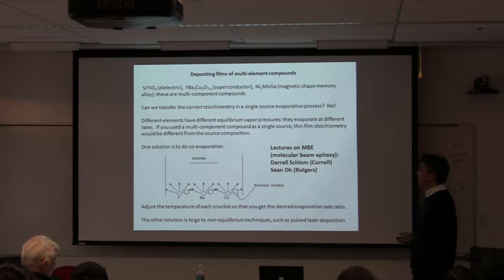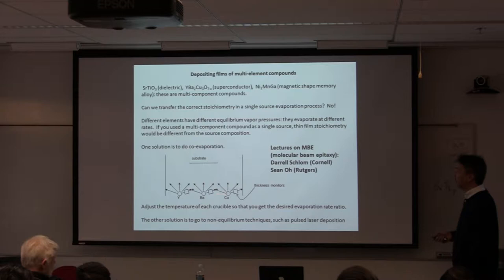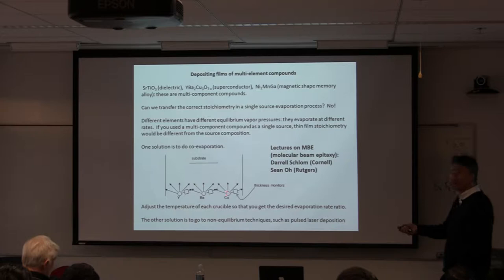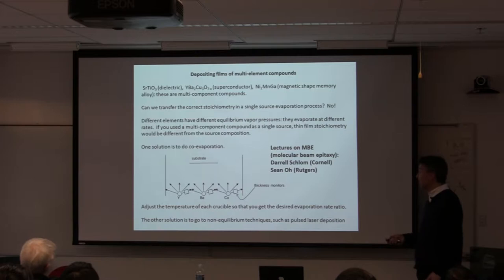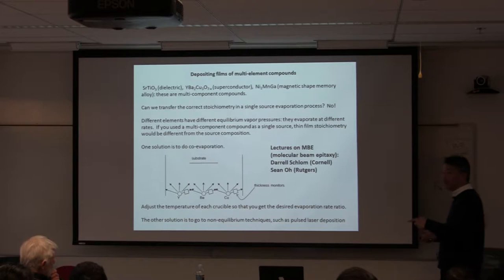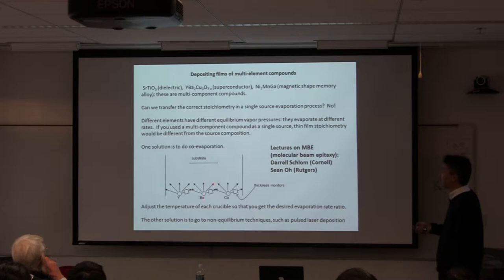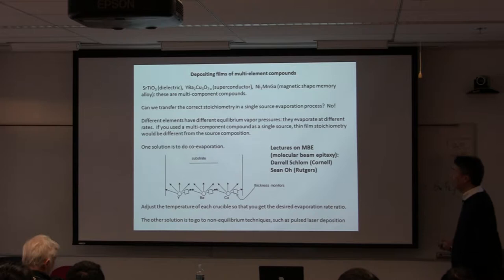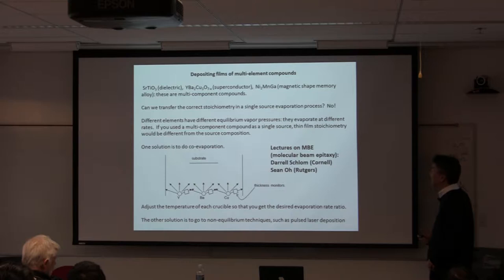To address this, we always had to do multi-source evaporation. In the late 80s, doing e-beam deposition for high-TC superconductors, I had to sweep between yttrium, barium, and copper with one electron gun, controlling power at each point via a thickness monitor to achieve the correct stoichiometric ratio. These days for MBE, that's a standard thing — you can do good control of the flux from each effusion cell.